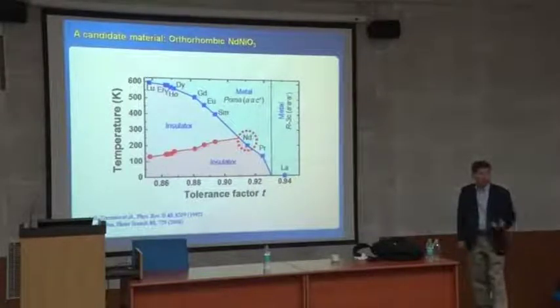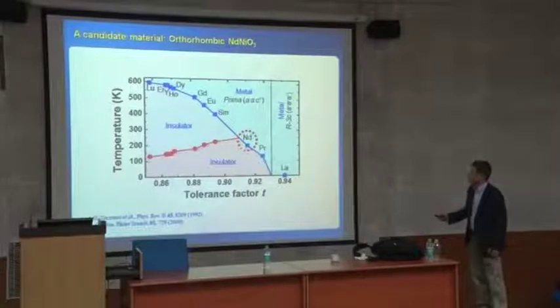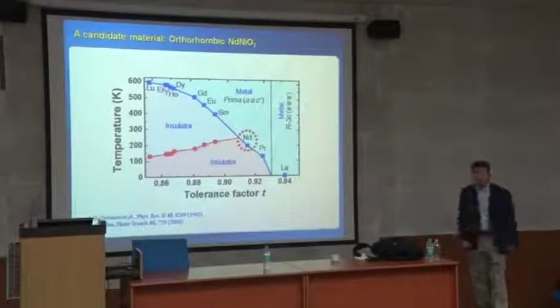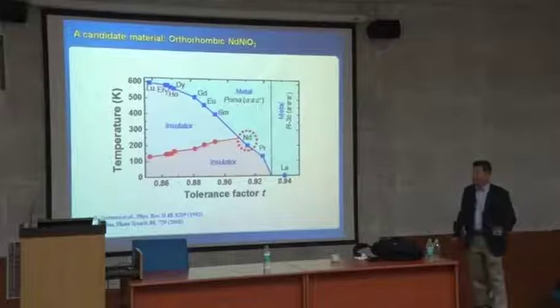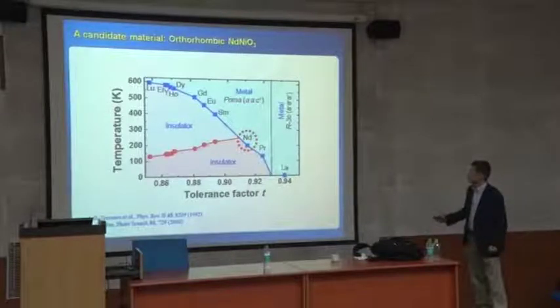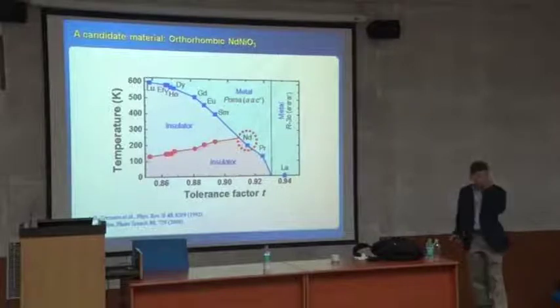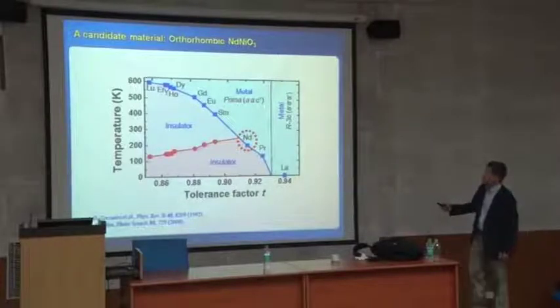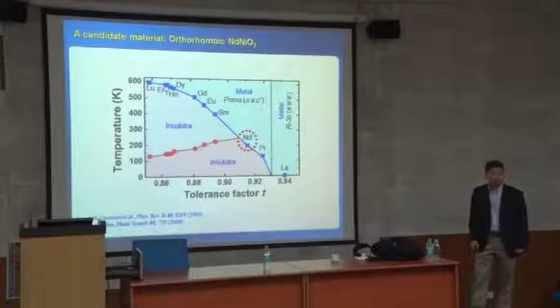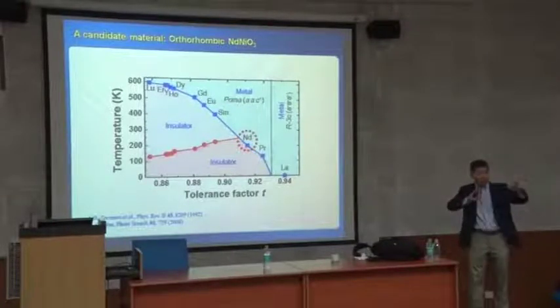But we want to have metals, but close to the metal insulator transition. And then you pick these two, okay, lanthanum and neodymium. But I'm going to talk about the neodymium system. But your pattern is minus, minus, plus. And then how can you actually stretch this tilting pattern?